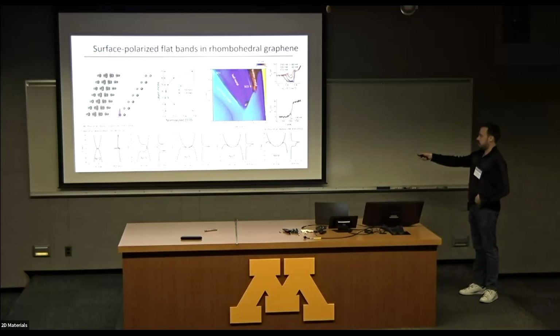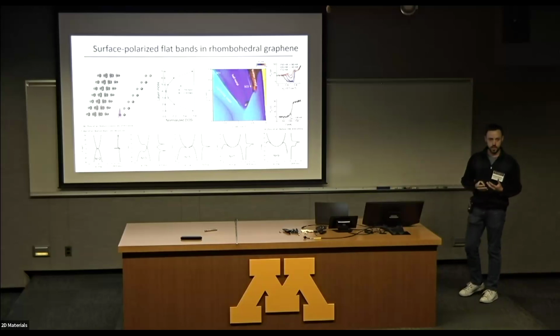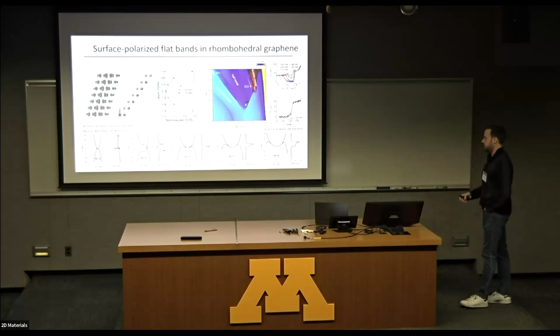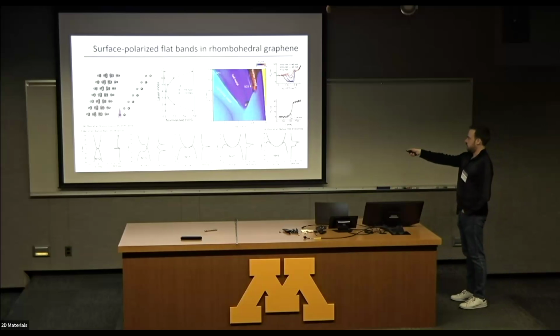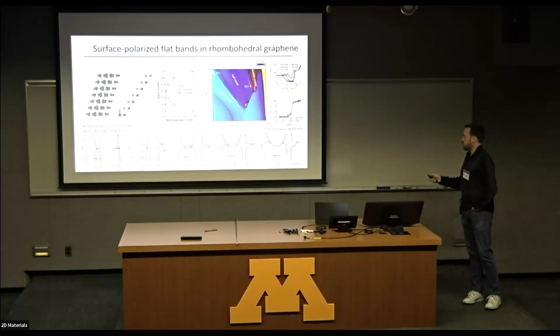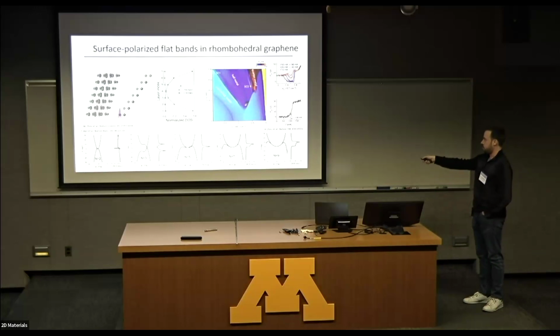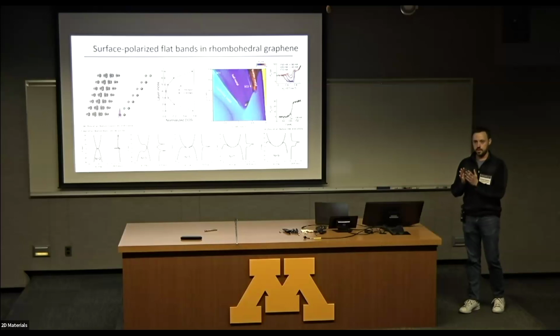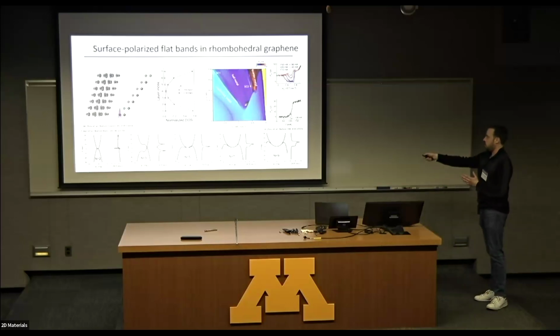And what you see is basically that within these flat bands, there's a proclivity to spontaneous spin and valley polarization in a sort of generalized Stoner instability that Allan talked about. So you'll see regions of quarter metals, half metals, unpolarized metals that you can access by changing the gate voltages. And importantly, what also often crops up is regions of sharply suppressed resistance that are indicative of very low temperature superconductivity, often at the boundary between two different isospin polarized phases or an isospin polarized and an unpolarized phase.